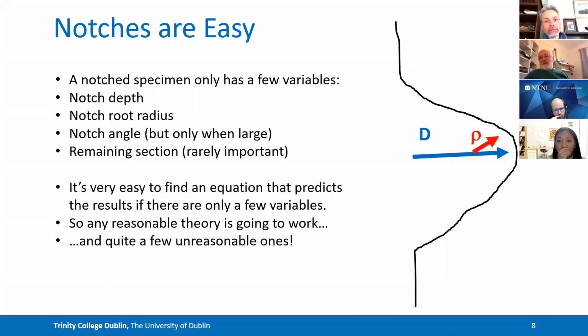So really, you've only got the depth and the radius. So it's not too difficult, looking at this rather cynically, to propose an equation that has a couple of constants in it. And you can fiddle around with the equation a little bit until it predicts the results from these experiments, because you've only got two variables, depth and radius. So any sensible theory that occurs to you is probably going to work, and it's probably going to predict the data reasonably well. I still see this quite a lot in the literature, that people say, "Oh, I have a theory about notch fatigue or notch fracture. Here are my results, and I can predict the effect of notch depth, or I can predict the effect of notch radius." But you have to ask yourself, are you being ambitious enough in what you're trying to predict? Really, you should try to predict a bigger range of stress concentrations, ideally also some real industrial problems, if you want to show that your idea works. Anyway, that's a comment there.